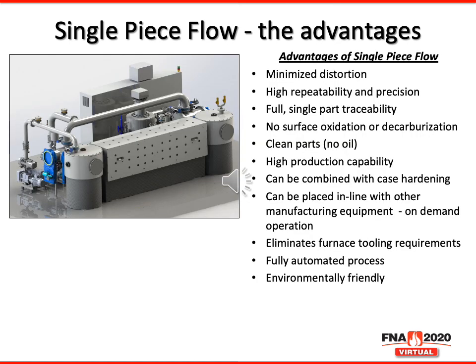And to recap, what advantages does single piece flow really bring to the table? Well, first, as we've spent a great deal of time talking about today, we minimize the distortion. Don't eliminate it, but we do minimize it. It has the ability for high repeatability and precision in heat treating. There's full single part traceability. The entire process occurs in a vacuum, so that means there's no surface oxidation nor decarburization. The parts will come out clean because there's no oil, unlike the press quenching process that we discussed.